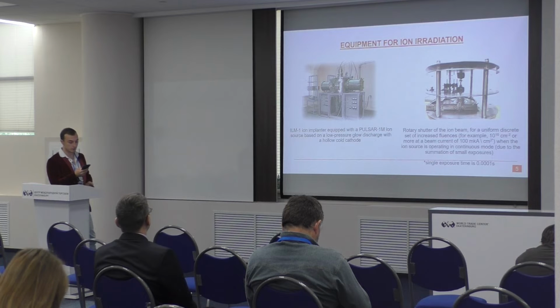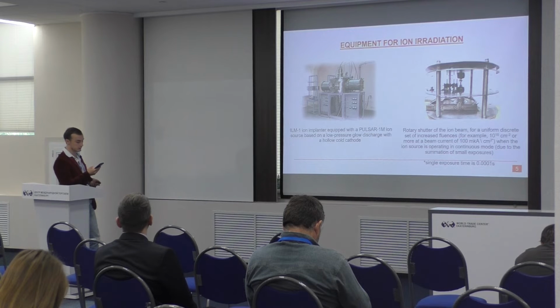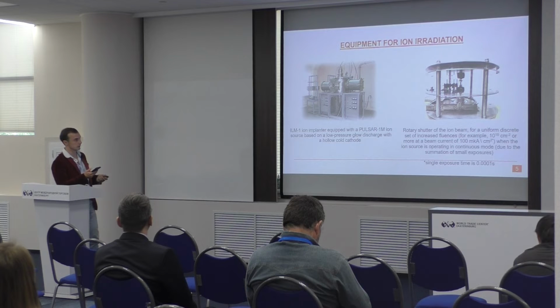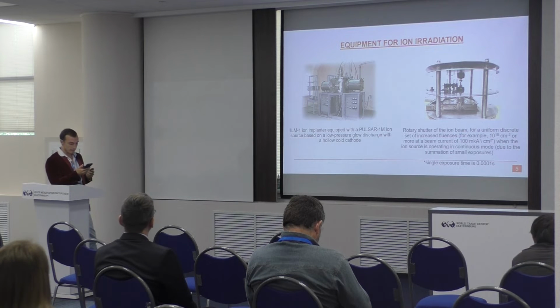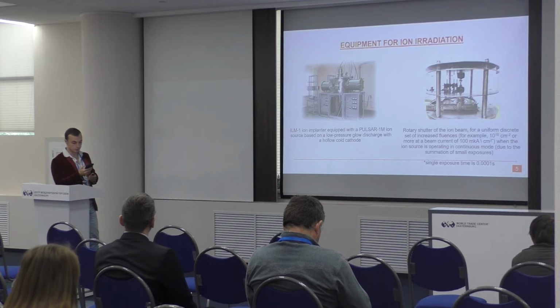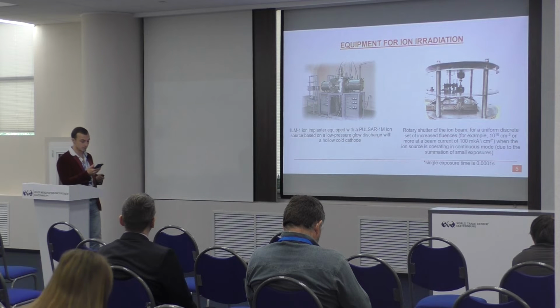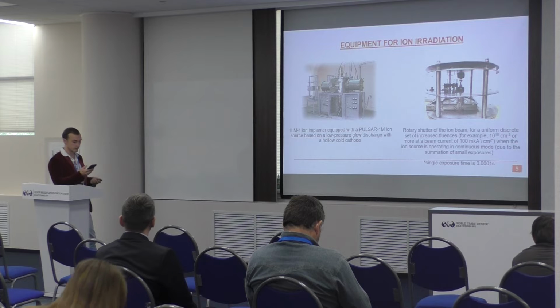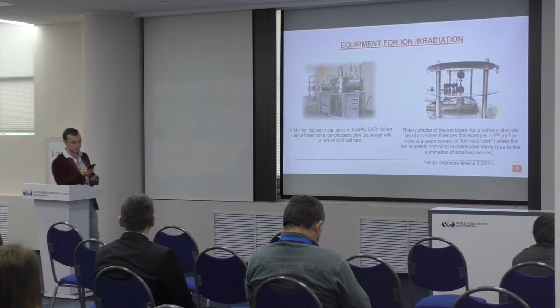The radiation was carried out by moving the samples under the ion beam, which made it possible to avoid significant heating of the sample during irradiation. In addition, in order to completely prevent heating of the sample during a set of increasing radiation doses, irradiation was carried out using a specially designed rotary shutter, which you can see on the screen. This shutter ensures a uniform set of fluence by summing small exposures. The duration of a single exposure is 1/10,000th of a second.